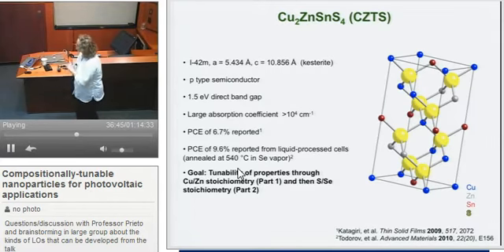But what's important about this compound right now is that it's a p-type semiconductor. It has a 1.5 eV band gap, so again in the optimal range. It has a huge absorption coefficient. So in theory, you would only need 250 nanometers of this material to efficiently absorb the solar spectrum. Power conversion efficiencies: this is basically if you shine light and you know how many photons are hitting your material and you collect the current, you can calculate your efficiency.